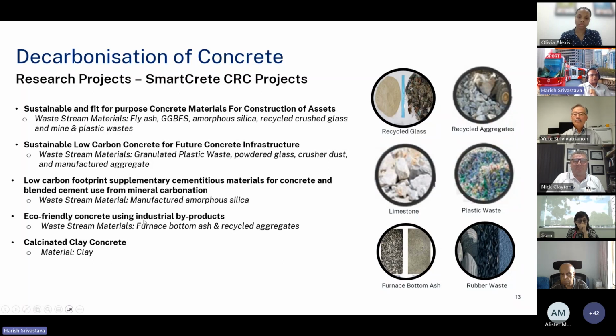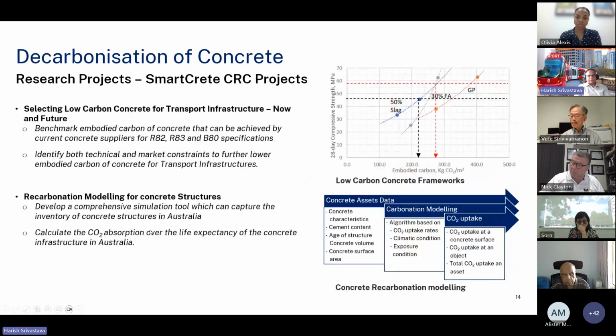And then furnace bottom ash, we are trying to develop a process as part of this research by which the furnace bottom ash could be used as SCM. Then we have recently started a project using calcined clay. At the moment, it's intended to be used as SCM, but it could be used as a full replacement of cement as well. Another thing which is not on this slide because it is a project in development: we are trying to develop a project for developing a design guide and specification for ultra high performance concrete to be used in infrastructure. So obviously that will support decarbonization.